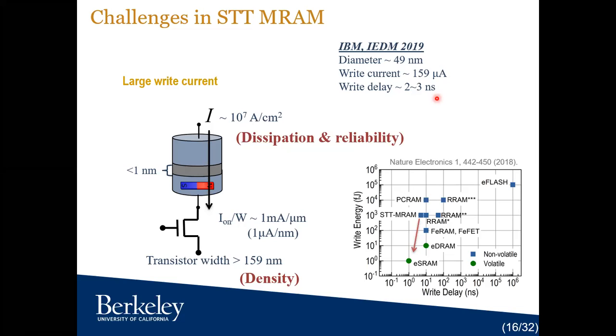So even though you can make your bit size closer to 50 nanometer, and these days people are scaling it much lower, like even 3 nanometer diameter has been discussed, the problem is that the write current is very high, and for that your transistor size has to be high, so your cell size is high. So that kind of stops you from further density scaling.